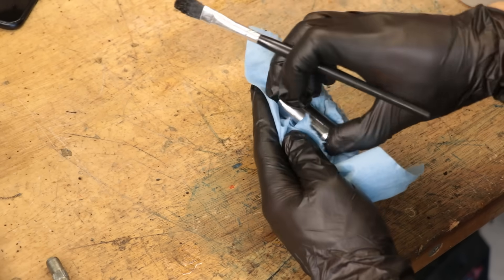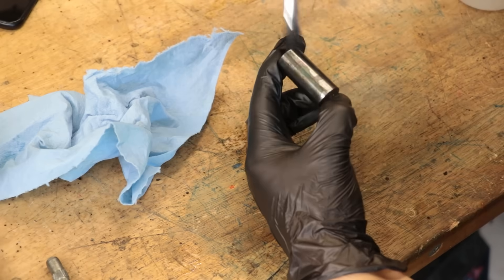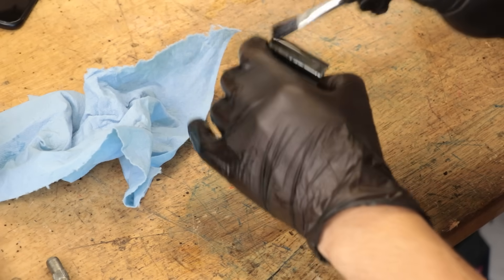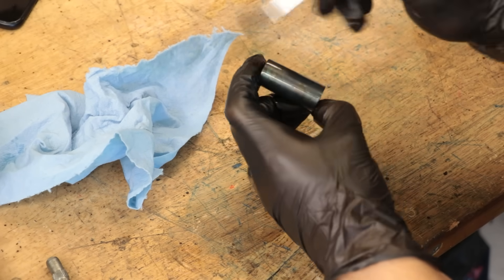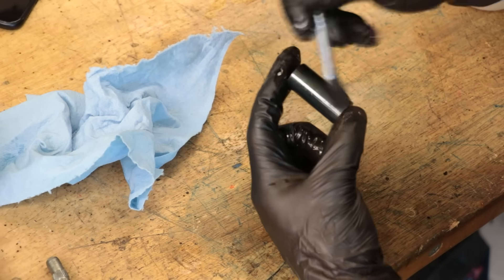I'll then get a small glass jar and pour in a small amount of cold blue. I'll use a small brush to coat the part with the cold blue, and you'll quickly see the part turn a deep blue-black. The aim here is to keep brushing until it's fully done reacting with the steel. Once that's done, you can simply rub it off.